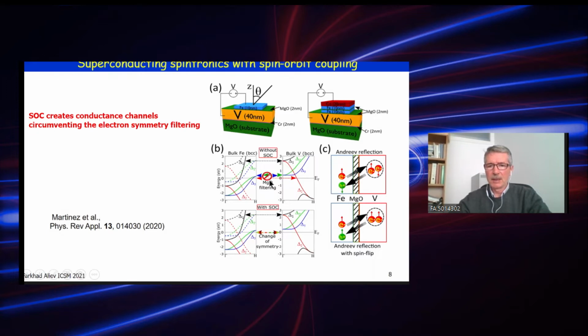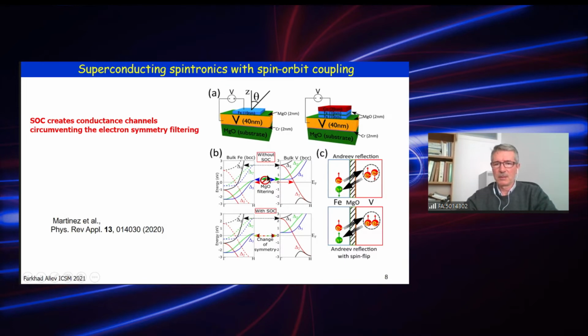So basically, theoretically, if you put these two materials in contact with spin-orbit coupling, there would be no current at all. Only the presence of spin-orbit coupling, which is able to change symmetry and mix different symmetries present in iron, creating delta-2 symmetries for example, is capable of creating a current channel. So all the current we investigate is current of electrons which have suffered spin-orbit coupling.